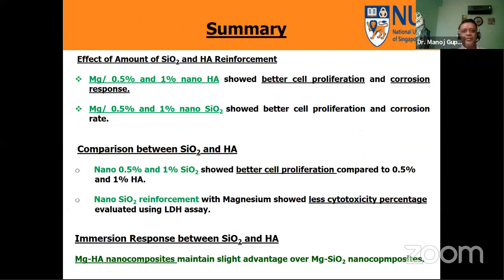So how do we summarize these results? First is the effect of the amount of silicon dioxide and hydroxyapatite reinforcement, and we found that both reinforcements at the same amount lead to better cell proliferation and corrosion response.